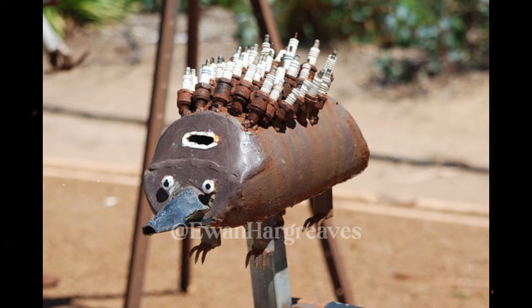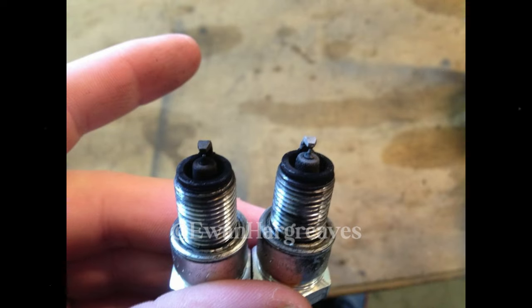In the 1960s, Champion introduced copper core center electrodes. Copper isn't a good electrode material by itself. It's too soft, would erode too quickly. But if you used a nickel alloy shell around a copper core, you got the best of both worlds. The nickel provided durability and electrical conductivity. The copper provided superior heat dissipation, pulling heat away from the electrode tip and transferring it to the shell and then to the engine cylinder head. This let engines run colder plugs without fouling, or hotter plugs without pre-ignition, depending on the application. AC responded with their own copper core designs.